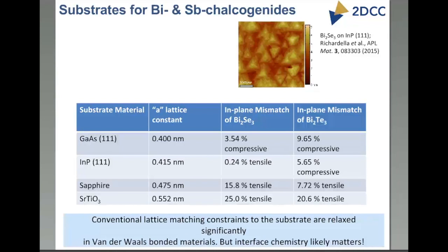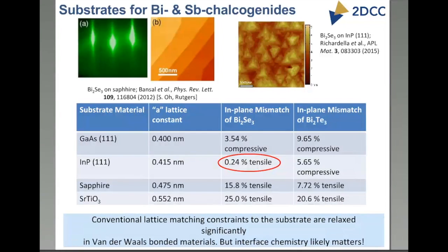The surface is not perfectly smooth. On the other hand, if you look at the next image here, this is from a group at Rutgers, Seongshik Oh's group, where they're carrying out growth of bismuth selenide on sapphire, and you look at the lattice mismatch on sapphire, and it's huge. Nonetheless, you look at the AFM of a thin film of bismuth selenide grown on sapphire, and they can get very smooth growth. So clearly, this indicates that there is something we still have to learn here about what are the conditions that we want to use in order to grow these layered structures such as chalcogenides on different types of substrates.